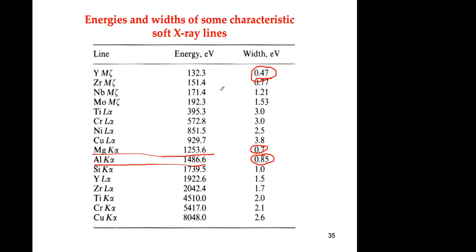Yeah. So with this energy, there's not much you can excite with 132 electron volts. But with 1.2 and 1.4 kilovolts, you can get very nice spectra of many elements. I mean, you can go to 8,000 with copper K-alpha or chromium K-alpha, but then your full width at half maximum is not very good. So that's the compromise they have, and they have selected this 0.7, 0.85 as the best one compared to all of this. We say a reasonable energy for excitation. And that's why they use magnesium and aluminum K-alpha.